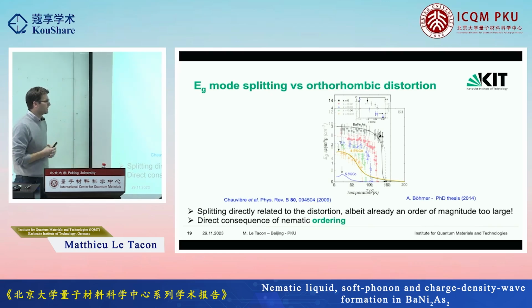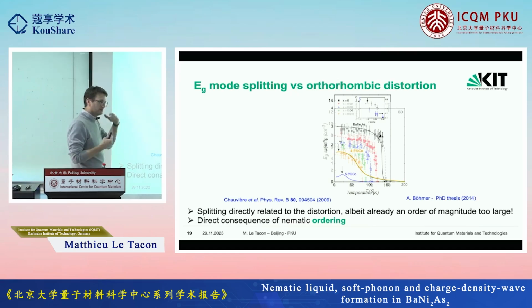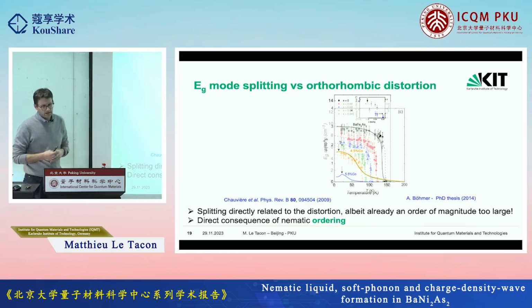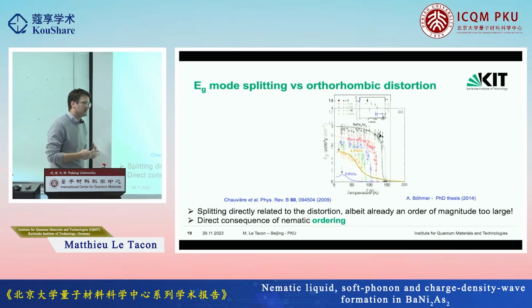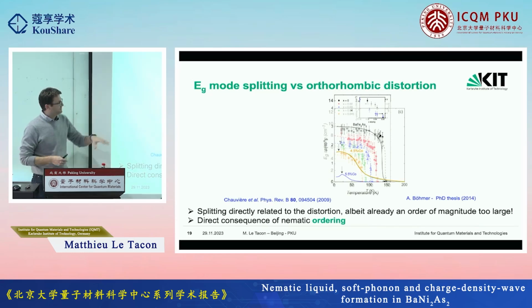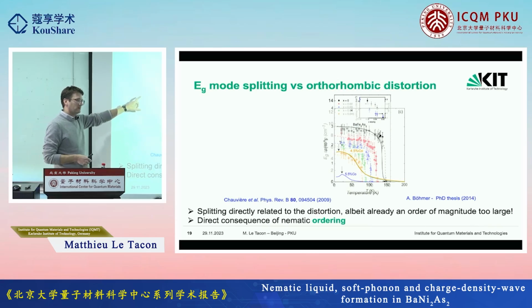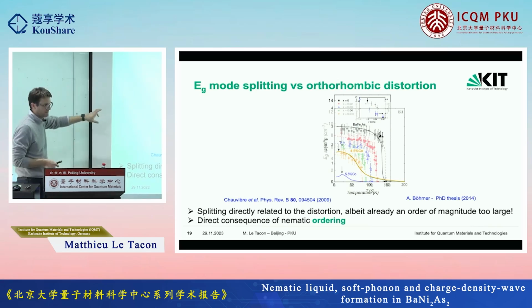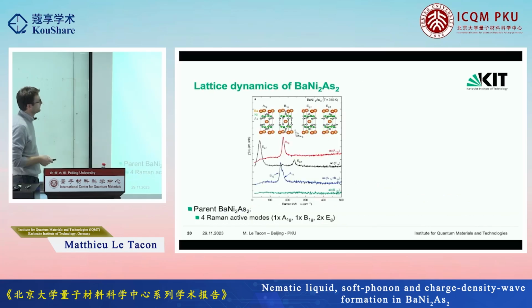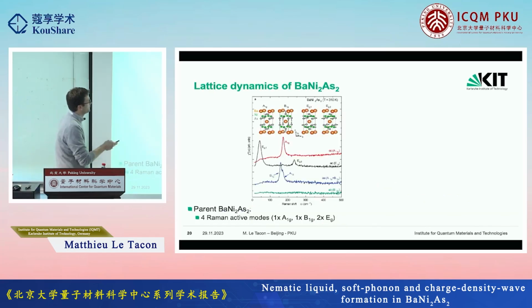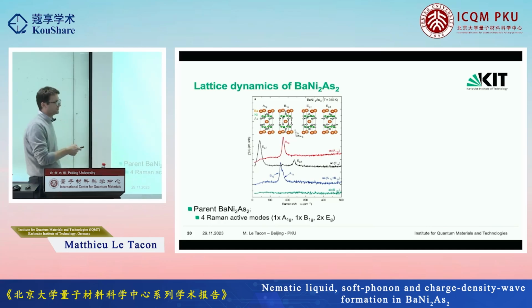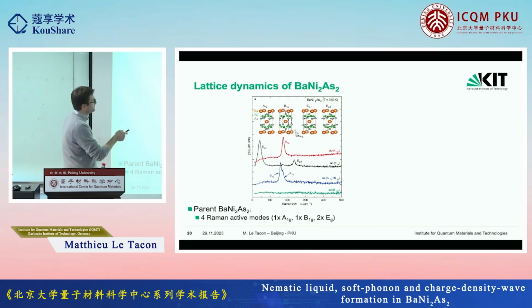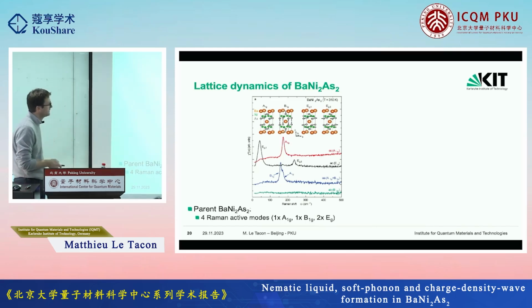So we thought, okay, in the nickel-based compound, we do have a structural distortion which is 10 times smaller than in the iron-based. But in the iron-based, the effect is so large that even a 10 times smaller effect we should be able to detect in Raman. So we started looking at those phonons in this BaNi2As2. So this is the same structure, so these are the same selection rules. So you get 4 Raman-active phonons, A1g, B1g, and 2 Eg modes, which are doubly degenerate. So we can measure them.